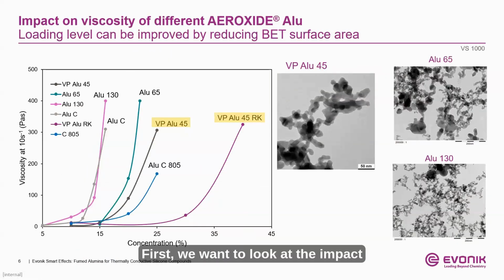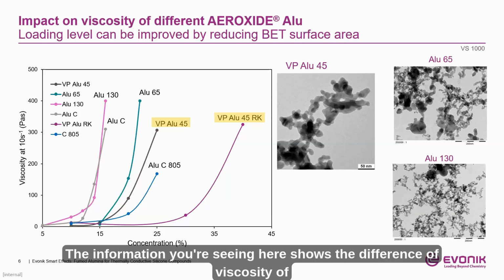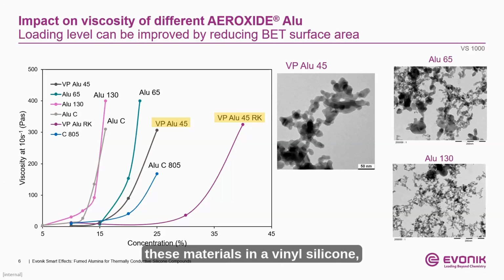First, we want to look at the impact of viscosity on the silicone compounds of these fumed alumina materials. The information you're seeing here shows the difference of viscosity of these materials in a vinyl silicone, specifically as a factor of concentration and specific surface area measured by BET analysis. Fumed alumina in this respect performs similar to fumed silica in that the thixotropic effects of these materials is reduced with a lower specific surface area, here indicated by the grade nomenclature.